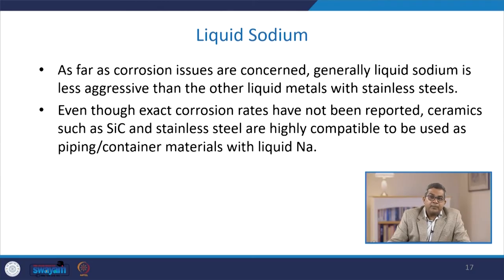Another issue is the high cost of liquid sodium—almost 4 times higher than solar salt. As far as corrosion is concerned, liquid sodium is generally less aggressive than other liquid metals with stainless steel, though exact corrosion rates have not been reported. Ceramics such as SiC and stainless steel are highly compatible for use as piping and container material with liquid sodium.